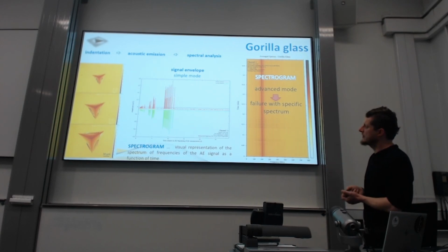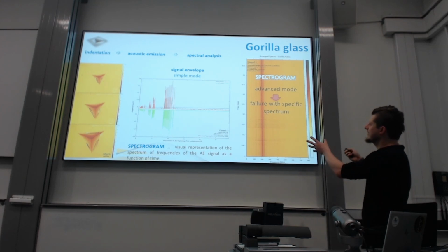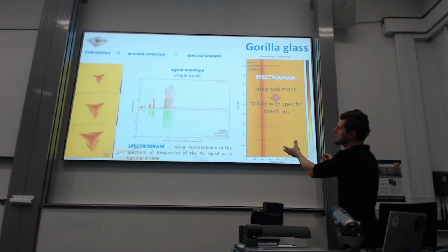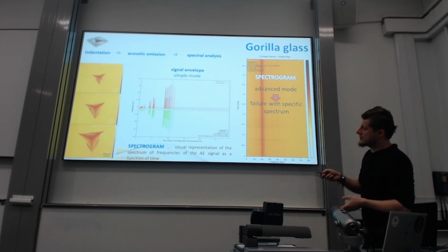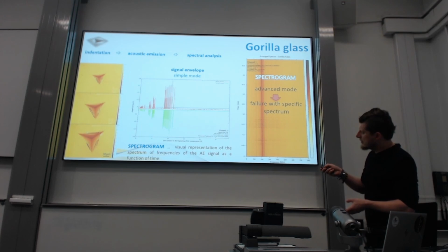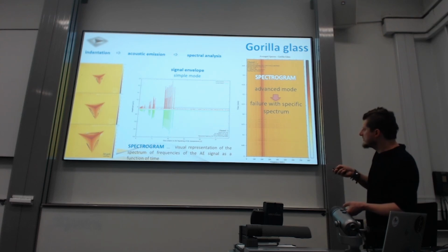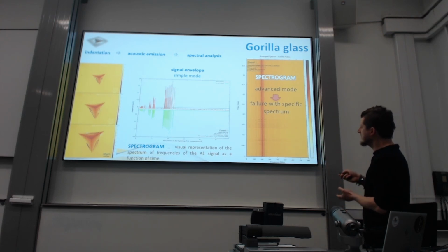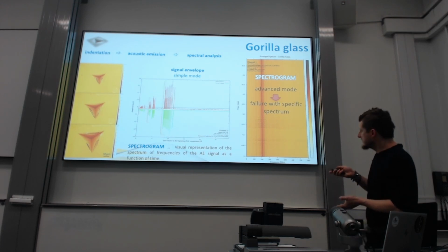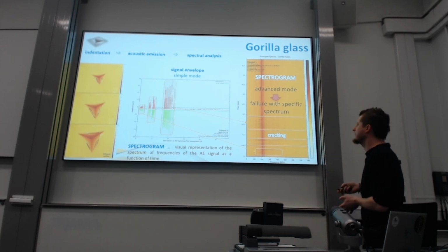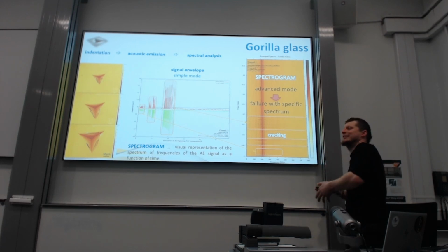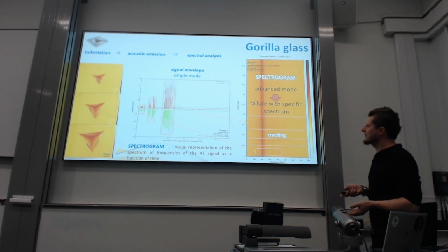So let's say one last image from me from indentation. This is an advanced type of output that we can have from our system. It's actually a 3D graph. We have indentation, some cracking in the loading phase, none in creep and none in the unloading phase. And what you can see here is the time record of the whole test. Frequency, so it's a spectrogram. We analyzed each hit and have a frequency, and the color means counts at that frequency. So you can see these hits in this spectrum. I don't think it's much of a scientific record. It's more like a nice record that can be placed in some publication. I just prefer the standard hit and frequency.